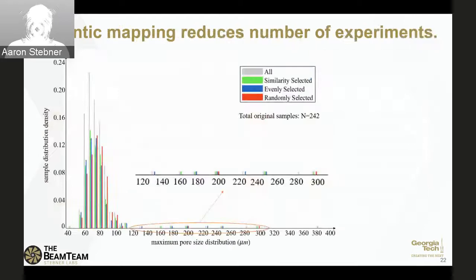what we were able to do, using that similarity clustered space, was better sample from the outlier space. And so that zoomed up scale bar there, from like 120 to 300 micron pores, the green there were our samples that we were able to take by first clustering things into similarity groups and then sampling the same number from each similarity group. In essence, the outliers only had 30 samples while the main distribution had hundreds of samples. But we forced ourselves to include data from 30 samples of each bin, for example, and we got a lot more representation from the outliers, and that helped us get to our confidence in our statistics and the tails of our statistics more rapidly than it would have had we used another design of experiments strategy like a uniform sampling or a random sampling or something else.